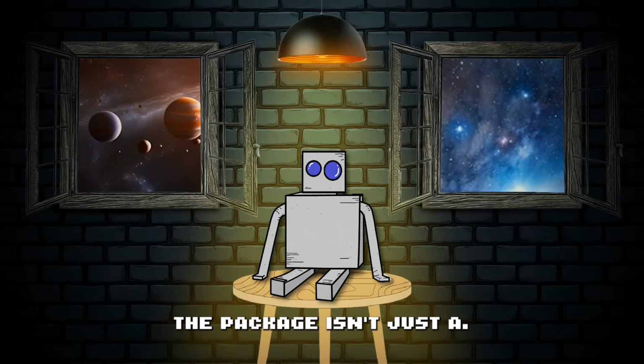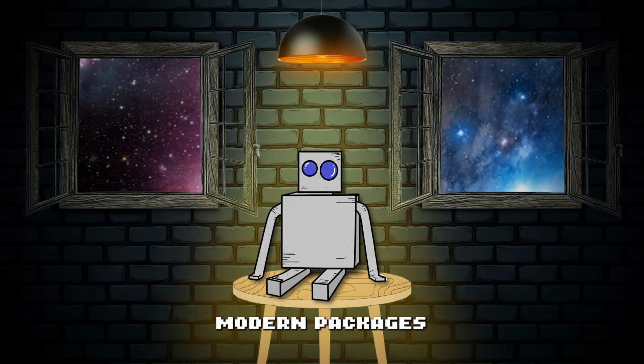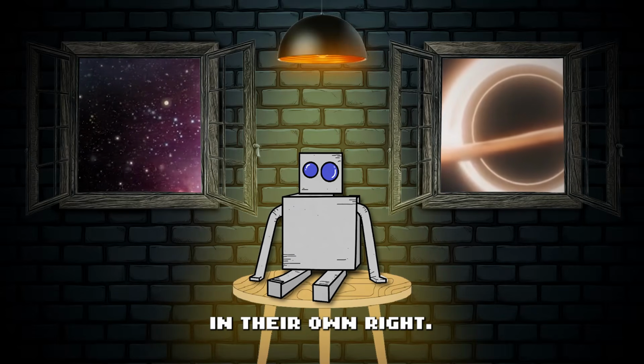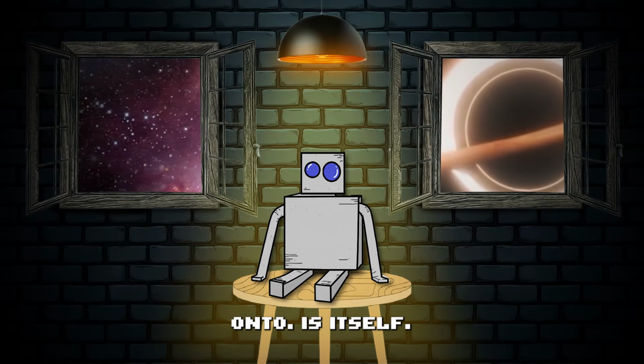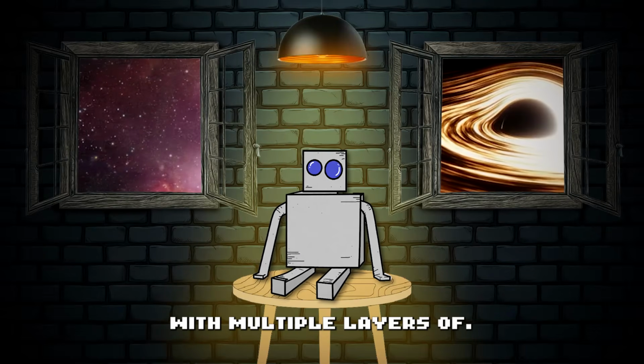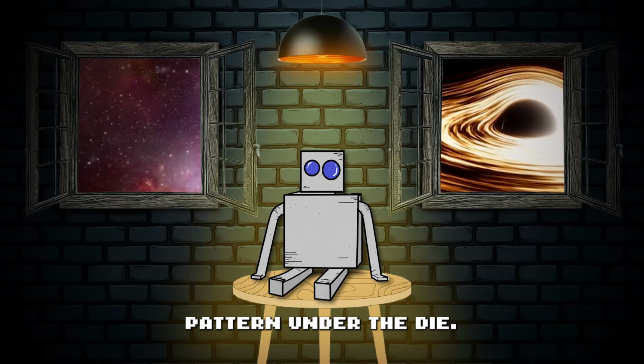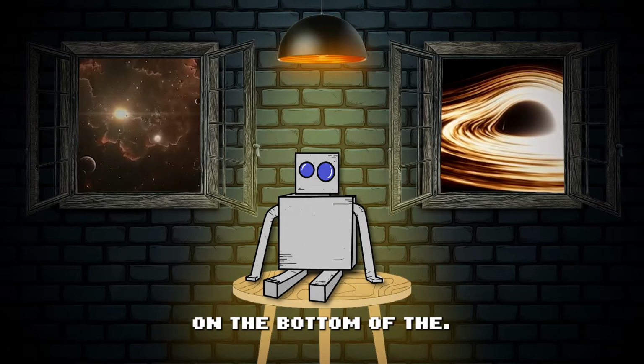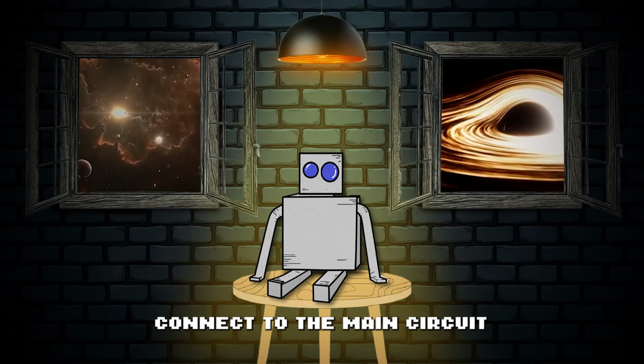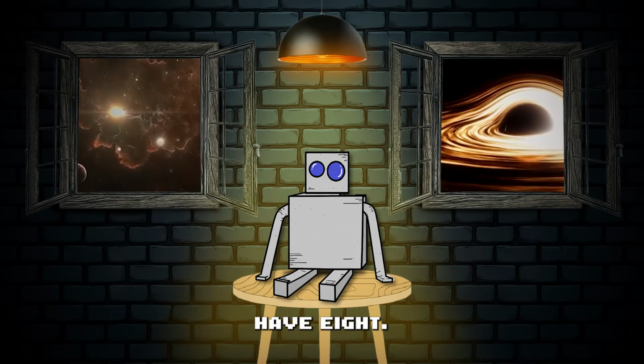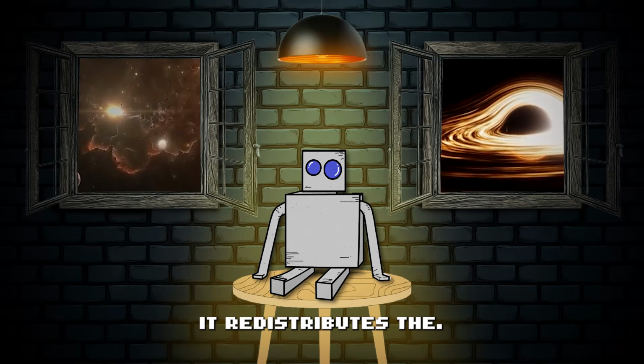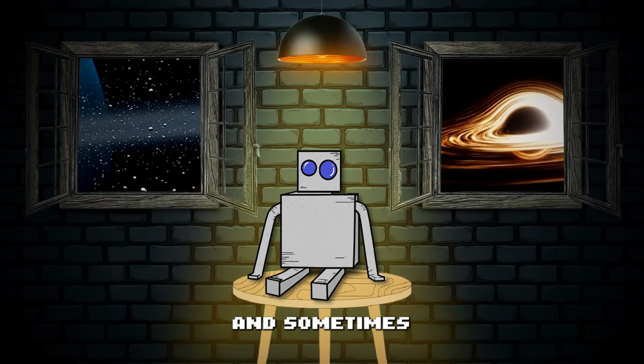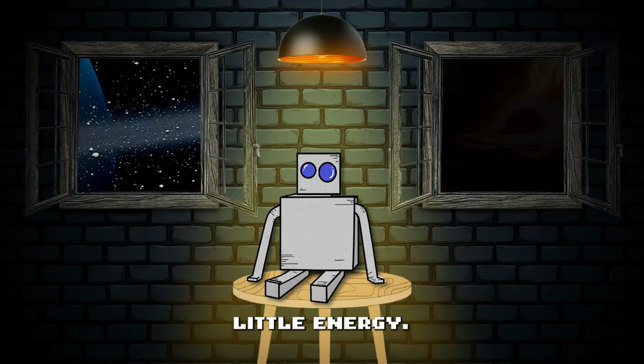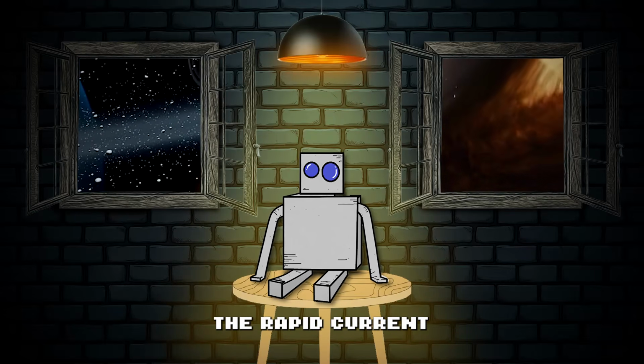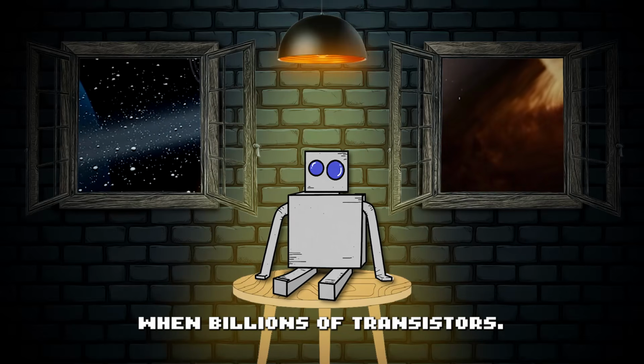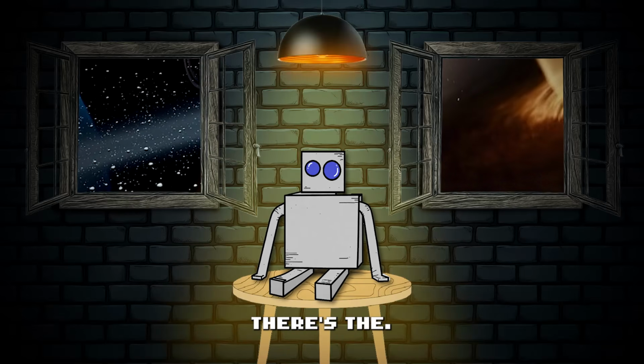But here's the thing. The package isn't just a passive connector anymore. Modern packages are engineered systems in their own right. The substrate that the die gets flip-chipped onto is itself a miniature circuit board with multiple layers of wiring that route signals and power from the dense bump pattern under the die out to the larger solder balls on the bottom of the package, which are what actually connect to the main circuit board. This substrate might have 8, 10, 12 layers of its own. It redistributes the connections, manages power delivery, and sometimes includes embedded capacitors for decoupling. Little energy reservoirs right there in the package to smooth out the rapid current fluctuations that happen when billions of transistors switch simultaneously.